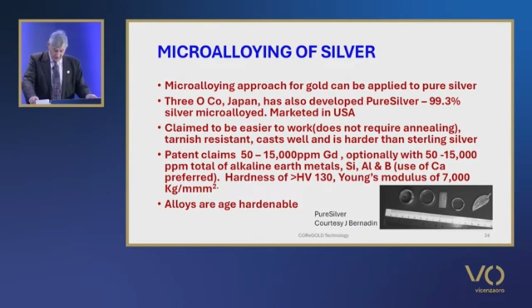The patent covers microalloyed gold, silver, palladium, and platinum materials. In the case of silver, an alloy of at least 80% silver is claimed, containing the rare earth gadolinium in the range of 50 to 15,000 parts per million, with optional further additions of alkaline earth metals, silicon, aluminium, and boron in the range of 50 to 15,000 parts per million in total, with hardness values of 130 Vickers or higher and a Young's modulus of not less than 7,000 kilograms per square millimetre.